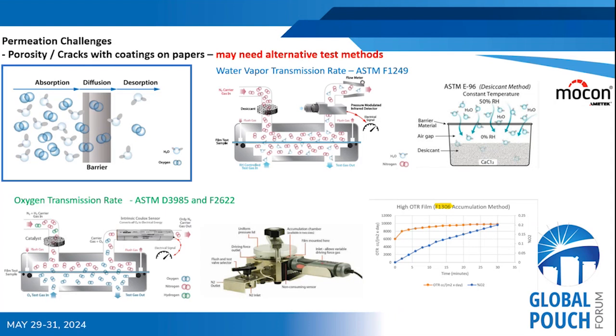For oxygen transmission rate, the testing itself is also similar to what I showed for water vapor. The material itself, again, would be this blue material here that's mounted in this diffusion cell. Oxygen will flow on one side, our nitrogen carrier gas flows on the other. Any oxygen that permeates through that material gets picked up by the nitrogen carrier gas stream, brought to our detector and quantified.